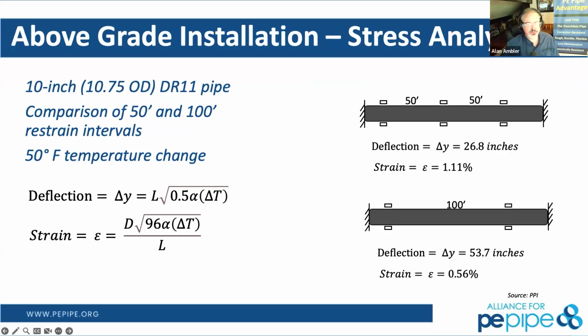So I'm going to use a term that Peter said earlier, which is forgiving. If we look at a 50-degree temperature change through the deflection and strain, while we may very well move quite a bit because of that massive temperature change through HDPE, our strain within the pipeline itself is not going to be as high as other pipe material. And this is very specifically due to the fact that the force required to stop the movement of the pipe isn't as high as other types of materials. That has to do with the modulus of elasticity, specific to HDPE. And as you can see here, 100-foot restraint, even though we may very well move 54 inches in between those restraints, the strain developed at the restraint itself is less than 0.56%.